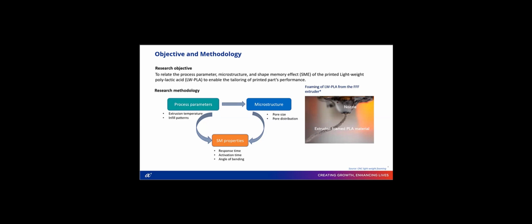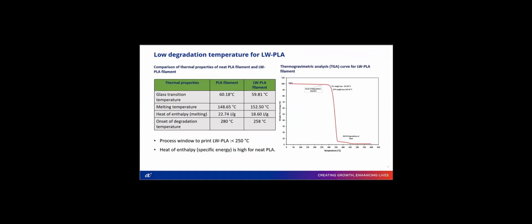So now our research methodology is controlling the process parameters to have different microstructures and to see how these microstructures affect the shape memory property of the lightweight polylactic acid. As a first step, we studied the thermal properties of the lightweight PLA and compared with the neat PLA filament, through which we understood that the degradation temperature of the lightweight polylactic acid is lower than that of the neat PLA filament. So we control the process window to print the lightweight polylactic acid.